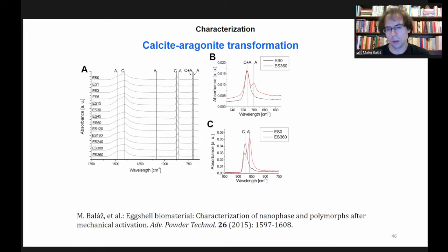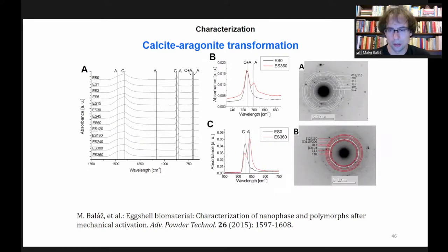We really devoted a lot of time to this investigation. We found out also that such details, for example, opening the milling chamber, can really impact the outcome, because when we opened the milling chamber and then continued milling, this transformation did not occur after 6 hours or was very, very small. But in this case, when we just left the eggshell to be milled for 6 hours, we observed the amount of aragonite phase to be around 60%. So mechanochemistry is, let's say, tricky sometimes, and all the details have to be investigated in detail.